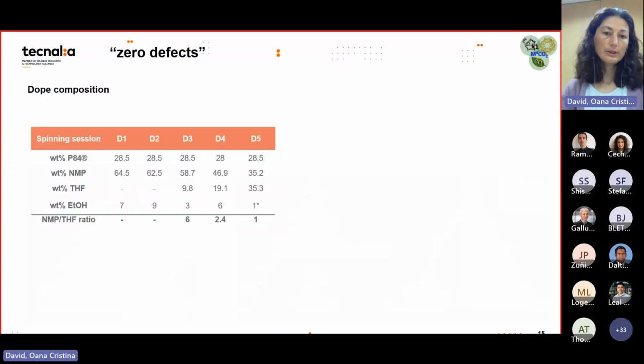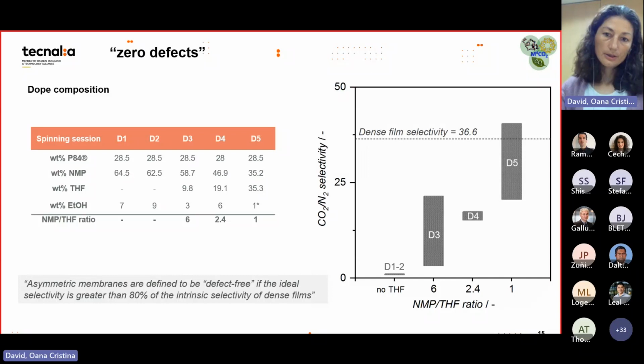And afterwards, we used different dopes to make the spinning experiments. So here we have different NMP to THF ratios in these dopes. And we had the best results with the one that had more THF inside, so when the NMP to THF ratio was equal to 1. And this was dope 5. The better results were when we had a selectivity closer to the intrinsic selectivity of this polymer in terms of carbon dioxide to nitrogen.